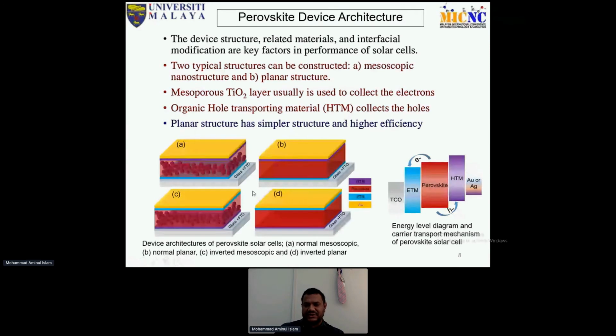So when we change the structure to the planar type, we see the efficiency is increased for the planar type compared to the mesoporous type, whether it's normal or inverted. So in both cases, most of the research is going on with these two structures. And here you can see how the carrier flows. When the perovskite layer absorbs the light, inside this perovskite layer, holes and electrons are created. Then the hole transport layer collects the holes, and the electron transport layer collects the electrons.